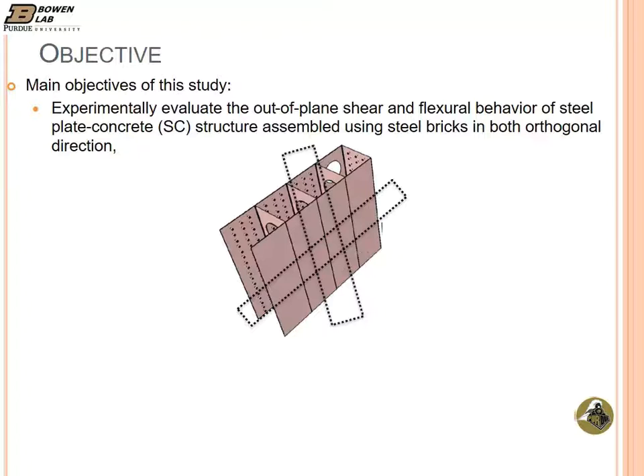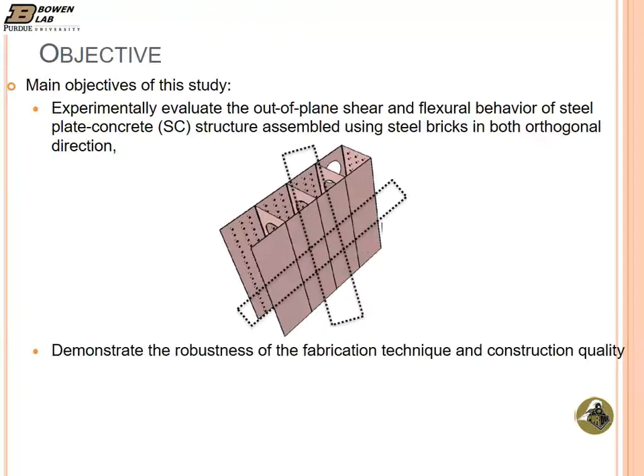So our objective was to look at the out-of-plane shear and flexural behavior, and because of that nature, we took two beam strips, one vertical and one horizontal, and then performed testing. We were looking at the strength, obviously shear and flexural strength, but at the same time we were testing the fabrication quality. The specimens were fabricated in this facility and welded together. The modules were put together, even the studs were shot, and then shipped directly to us. The only thing left for us to do was to cast the concrete and test the specimens.